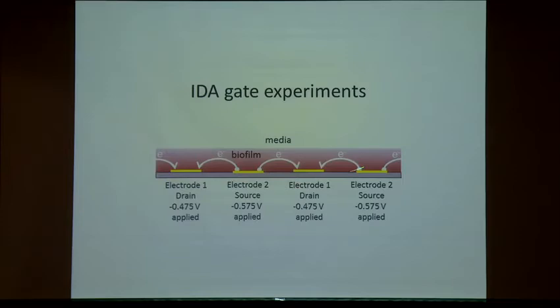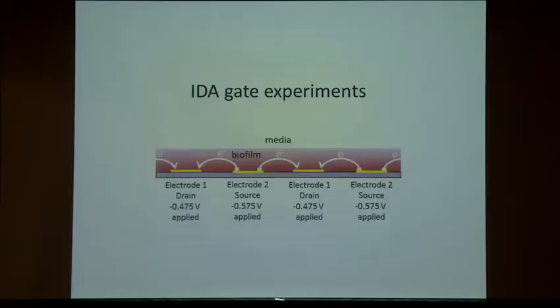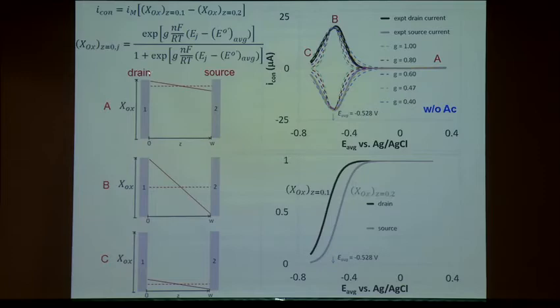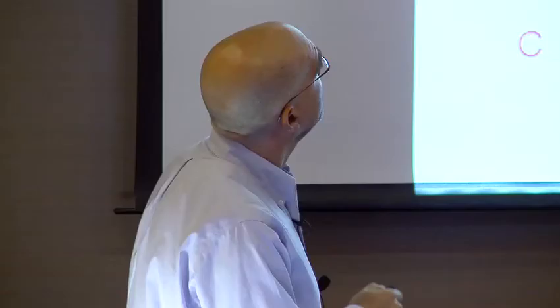Here, I'm putting a bias between the electrodes. So in a voltammetric picture, I would be simultaneously sweeping both potentials, going from positive to negative potential and then back down, but at the same time maintaining a bias between them. As a result, I should be able to drive charge from the more negative electrode through the biofilm to the more positive electrode. In that case, I'm defining the oxidation state of the biofilm at both electrodes, pinning what those oxidation states are, and then creating the concentration gradient between the electrodes that should be driving electron transfer through the biofilm.